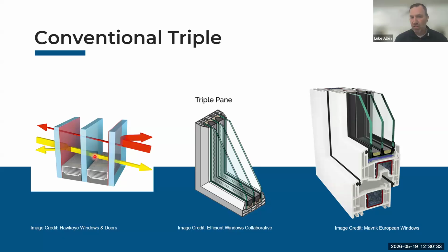I had mentioned before that condensation resistance is primarily a relationship between the relative humidity within the building as well as the surface of glass temperature. Low-E coatings are primarily a metal-based product. Sometimes they're single pass, sometimes double pass, sometimes triple pass, and even beyond. In a dual pane system, to get two low-E coatings, one is typically on surface 2, what we refer to as a soft coat. The other is on surface 4 and referred to as a hard coat. The reason why it's a hard coat is for those who clean their windows. Obviously, they don't want it to wear off, scratch, those sorts of things. So being metal and being room side affects the center of glass temperature. So you have more of a preponderance or potential of condensation. So typically when you have a dual pane with a dual low-E coating, your condensation resistance suffers because of that.